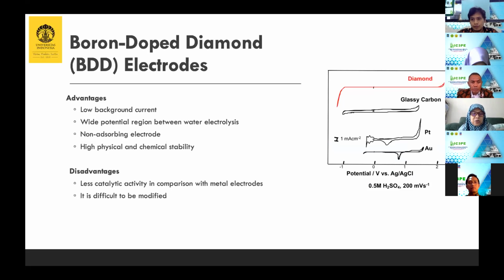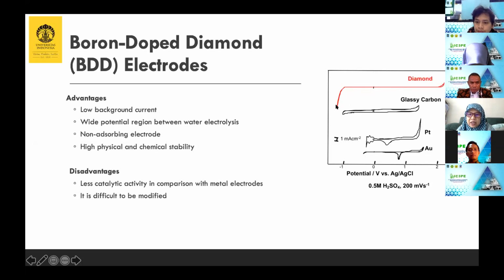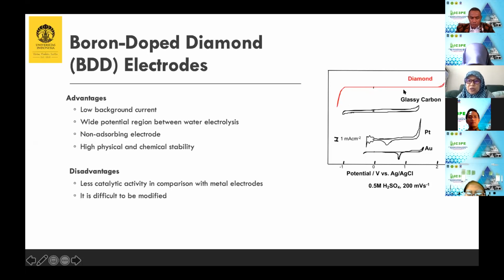And here in this picture is the cyclic voltammogram of diamond compared to other electrodes like glassy carbon, platinum, and gold. We can see that if we run the potential from very low potential to very high potential, we get electrolysis of water. This is reduction of water to hydrogen. Here is oxidation of water to oxygen. And between these potentials, we can oxidize or reduce other materials.